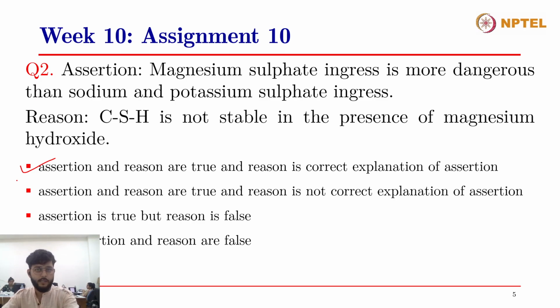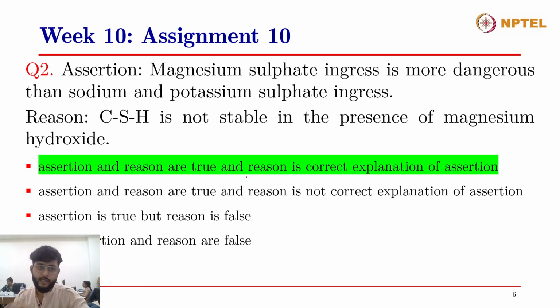The assertion is true. That is, magnesium sulfate is indeed more dangerous than sodium and potassium sulfate ingress. And the reason is that CSH is not stable in the presence of magnesium hydroxide. When magnesium sulfate ingress occurs inside cement or concrete, it produces magnesium hydroxide. The magnesium and the sulfate ions react with the OH minus ions, that is the hydroxyl ions inside the concrete coming from the pore water, and they precipitate magnesium hydroxide, which we call brucite, Mg(OH)2.